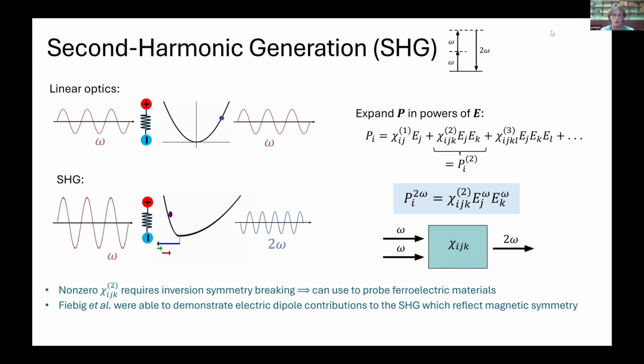So the way that we are using this to look at the symmetry of the material is by imposing selection rules on the tensor. So really, it's a question of can you find a tensor that is sensitive to the symmetry breaking you want to look for? And it happens to be this particular second order effect that is useful for that. Finding the ones that also respect the magnetic symmetry is a bit trickier. And of course, you can have magnetic dipole contributions to SHG, which are much weaker.